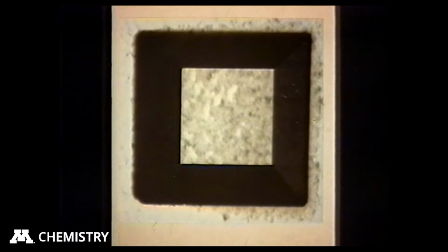And this crystal is like a little truncated pyramid coming out at you. So here's the top face, and then the side faces are here, and they're also transparent. It's just that in the lighting you're seeing they look opaque. But this is transparent from every direction. It's a beautiful large tetragonal crystal, and this one is a co-crystal of imidazole with binaphthol, 1,1' binaphthol. And there is nothing that suggests 4-fold symmetry about either of those molecules or the pair. So I have no idea why this grew in a tetragonal crystal.